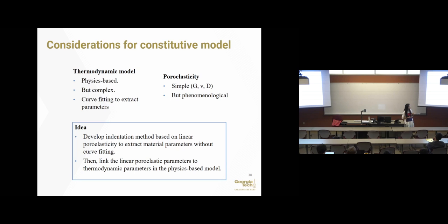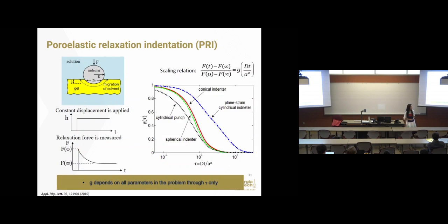But these material parameters are phenomenological. But we want to take advantage of both. So the idea is, we develop this indentation method based on linear poroelasticity. So we can get a simple solution, extract the material parameters without curve fitting. And then we will try to link these poroelastic phenomenological parameters to the physical parameters in the thermodynamic theory.